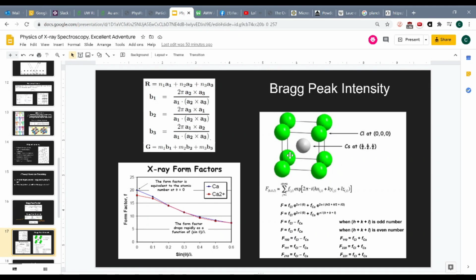The atoms, in this case, if you were to represent the primitive unit cell of this, you would only have one chlorine and one cesium inside of it. So in this case, they're only summing over chlorine once and then over cesium once. So you have your form factor for chlorine, then you know that the chlorine is located at 0, 0, 0, and that means that H is 0, K is 0, L is 0, it's just e to the 2 pi i times 0, so this just goes to 1. And then for cesium, you have 1/2, 1/2, 1/2, so it becomes e to the i pi times (H plus K plus L).